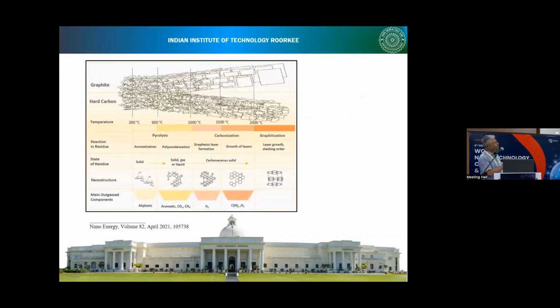If we have a soft material like graphite, at a higher temperature of 1000 plus, graphitization takes place. Whereas for hard carbon, even if we go to 1000 plus degrees centigrade, it is not fully graphitized. It is gradually graphitizing, but that takes very high temperature. Therefore, it is a non-graphitizable material. So it is a mixture of graphitic and non-graphitic, what we call turbostratic graphitic. And this material is actually used for the anode materials of sodium-ion batteries.